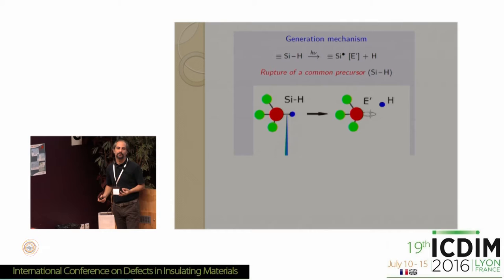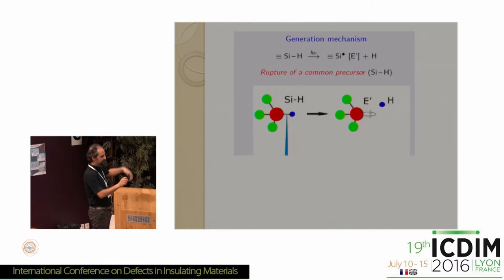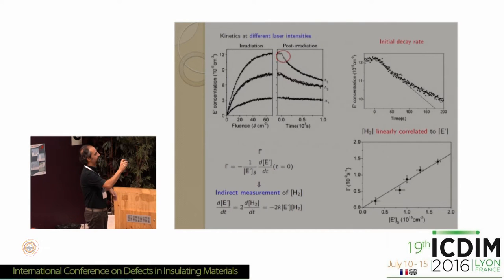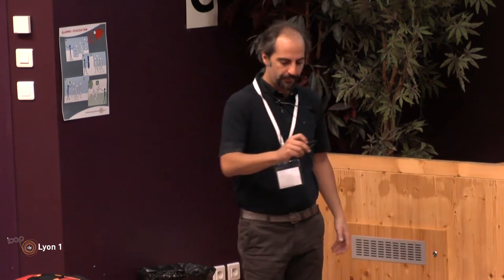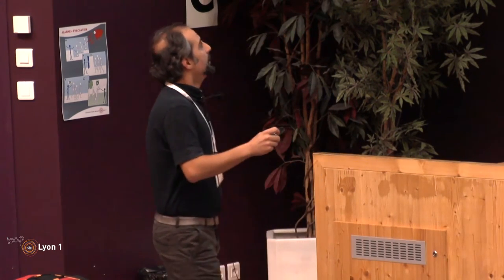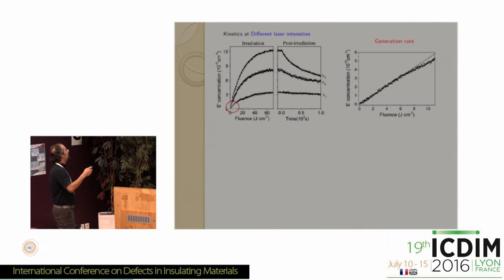Then hydrogen atoms are very unstable at room temperature in silicon dioxide. They easily react with other atoms to form molecules, H2. And what we observe in the post-irradiation stage, this decay, is due to the recombination of E prime centers with hydrogen. Okay.